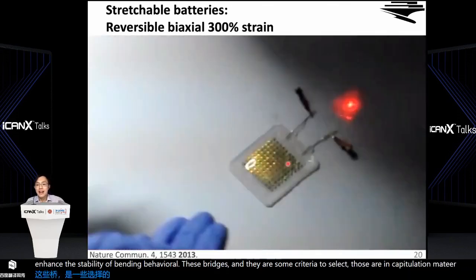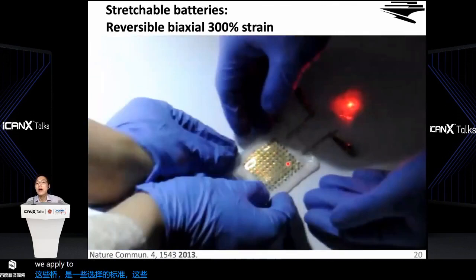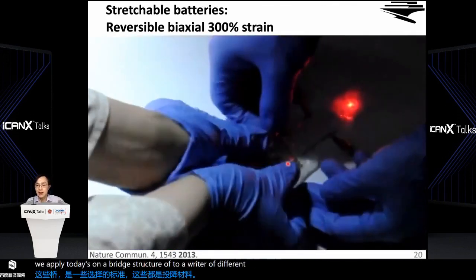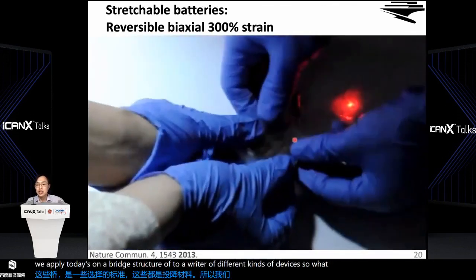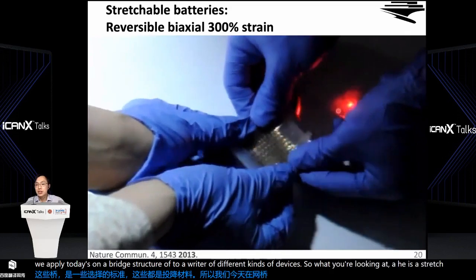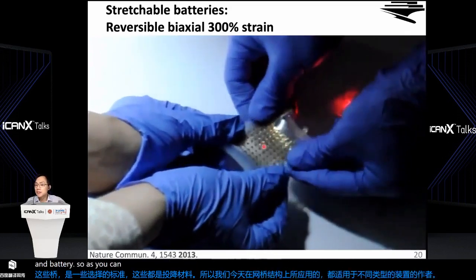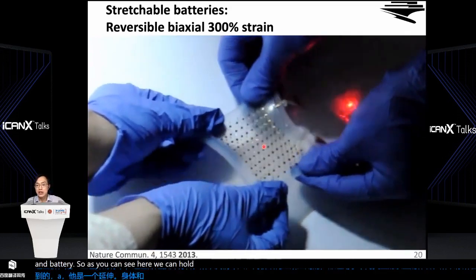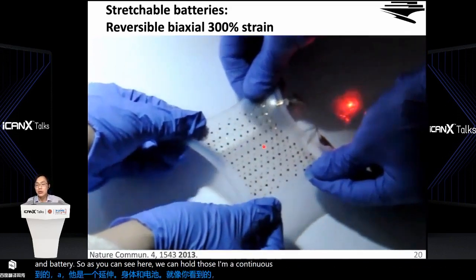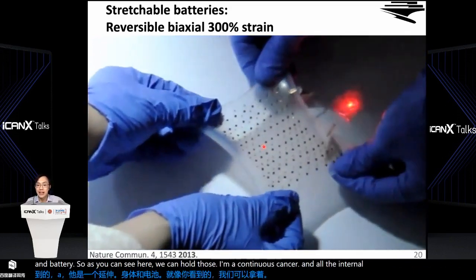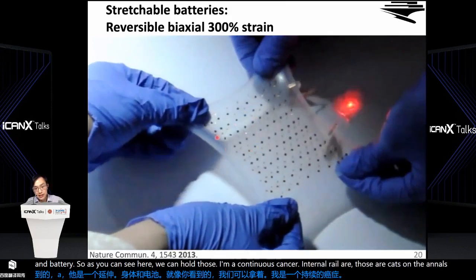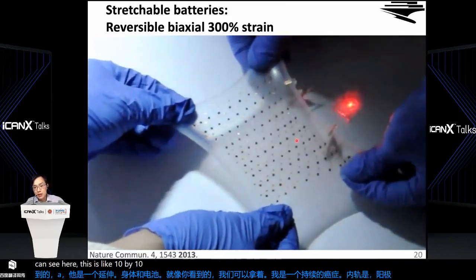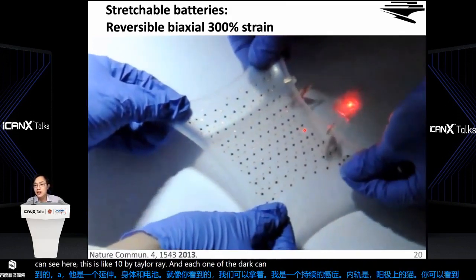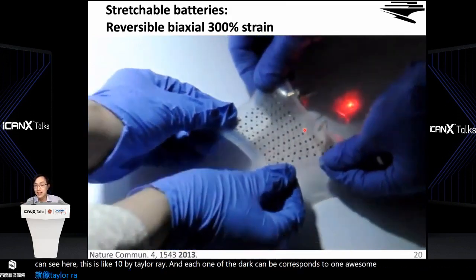So we applied this island bridge structure to a variety of different kinds of devices. So what you're looking at here is a stretchable lithium battery. So as you can see here, we decompose those continuous cathode and anode into an array of those cathodes and anodes. And you can see here, this is a 10 by 10 array, and each one of the dots corresponds to one small cathode island and anode island.